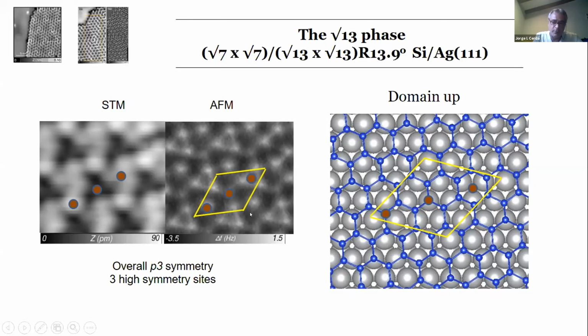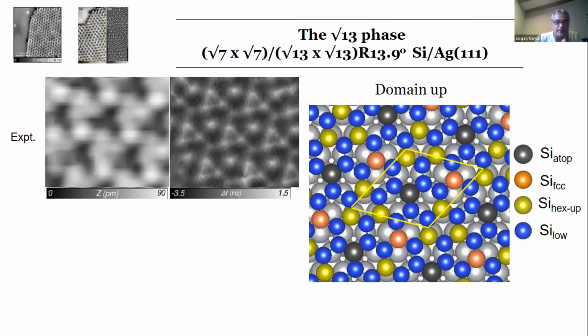Still, we can end up with lots of models, but the use of symmetry really reduces the number. Just a few tens of models instead of having to try hundreds of them. This is the one that we obtain as the most stable one. Now we have up to 4 types of silicon atoms, again with very high ones that are sitting on top sites. Now we have this hexamer structure again, back with the hexamers. This time they are around an HCP site, and we now have an extra atom which is in an FCC site. Okay. After many calculations, this is the structure that shows the best energetics. Okay, the most stable one.